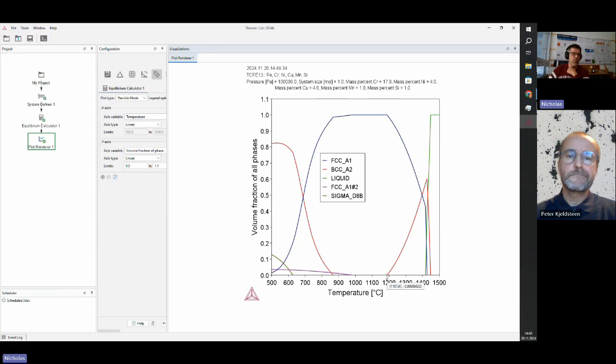And then I have a range somewhere between just under 1,200 degrees and just under 1,000 degrees, where it's single phase pure austenite, right? But here already the first questions start, right? If I form delta ferrite, will it decompose? Because for carbon steels, delta ferrite decomposes very quickly, but for stainless steels, it mightn't. But whether you form delta ferrite or not also depends on the cooling rate, because you can undercool the melt and directly solidify it as austenite. So these are all sorts of other interesting questions.